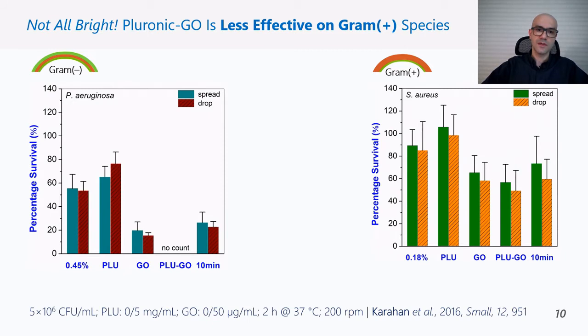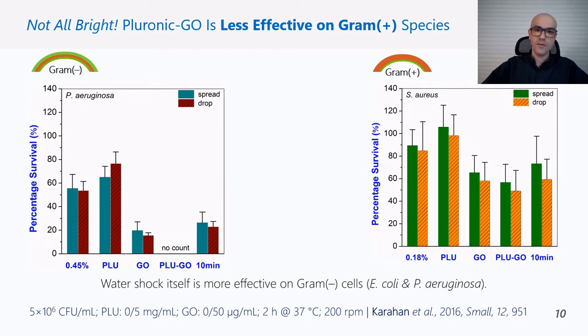Finding such a simple, effective, and potentially biocompatible formulation was exciting for us, but unfortunately, pluronic stabilized graphene oxide showed less activity on gram-positive cells. As I emphasized earlier, gram-positive cells do not have outer membranes and have much thicker peptidoglycan layers. Therefore, we wanted to explore the role of peptidoglycan layer further.